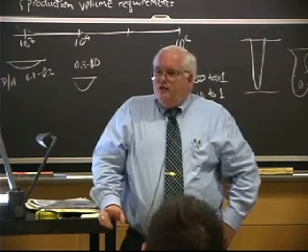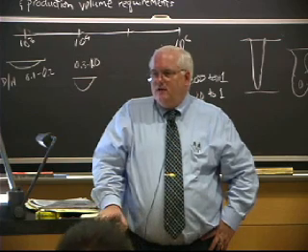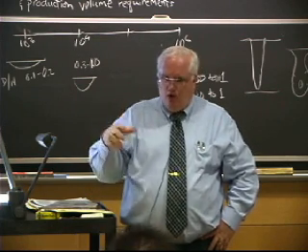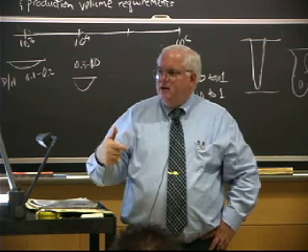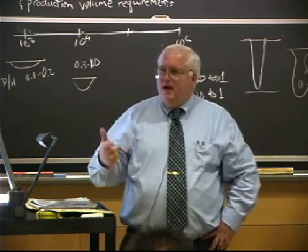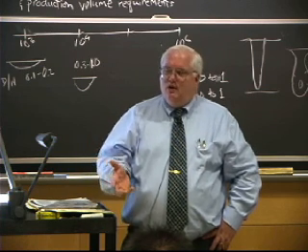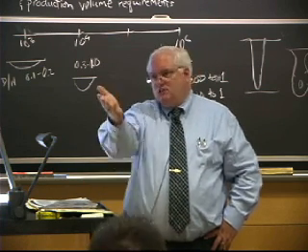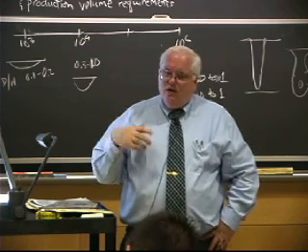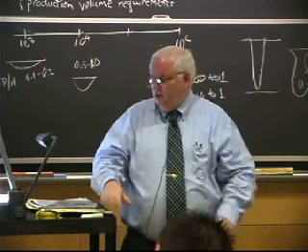That's DC. There's an AC technique, whereby you go to a high enough frequency and you can do induction heating. Induction heating is where you have a high frequency coil around your metal part, and you induce an alternating magnetic field. The magnetic field creates eddy currents within the part. So the alternating AC field induces current flow within the part. So it's still electric current, just like you said, only it's AC driven. There's actually no contact with the part, and so you can heat a part by induction. And so people do induction heating and forge welding and things like that.